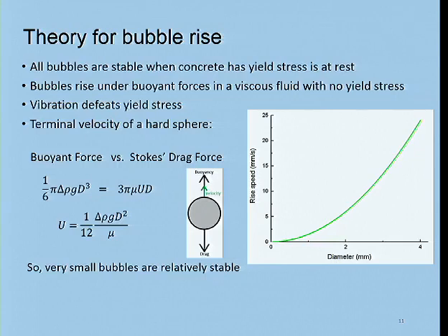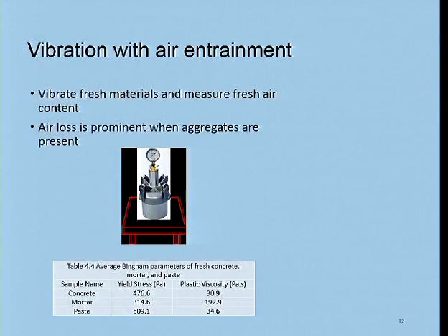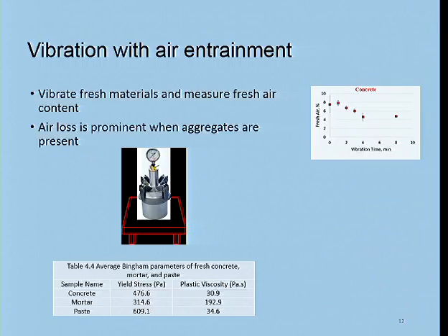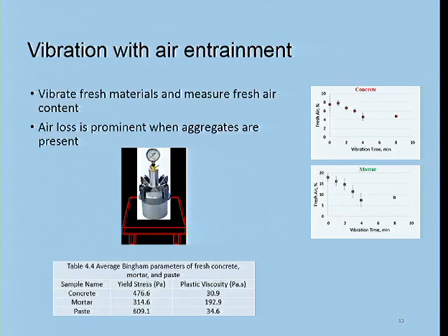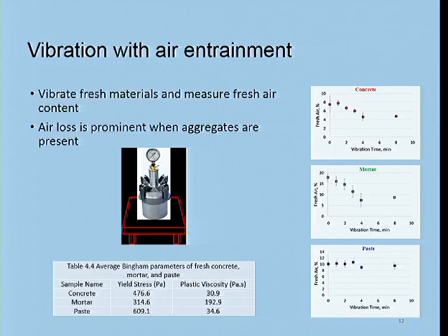And so we wanted to see how this worked, and we were able to do experiments of concrete under vibration with air entrainment. We did these tests by putting an air meter with a concrete sample on a vibration table, and we could see air decreasing with time. So vibration time is on the x-axis, the air content on the y, and you see this drop with time of vibration for concrete. And if you did it with mortar, that is just the paste and the sand, the fine aggregate, we see the same kind of drop. But if you do a test on just air-entrained paste alone, you see almost no loss of air when it's vibrated. Well, that's interesting, isn't it?